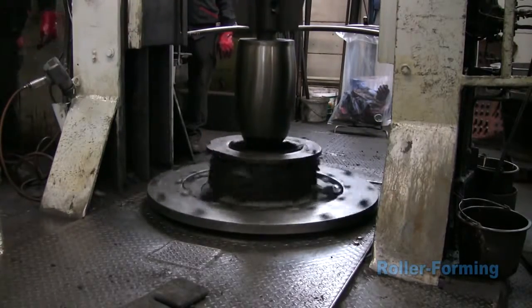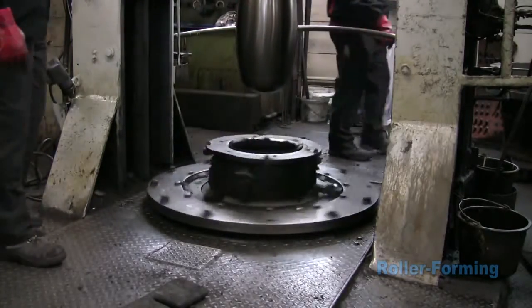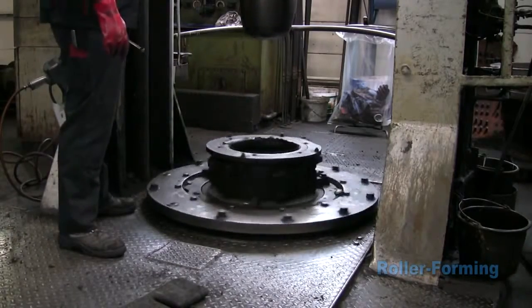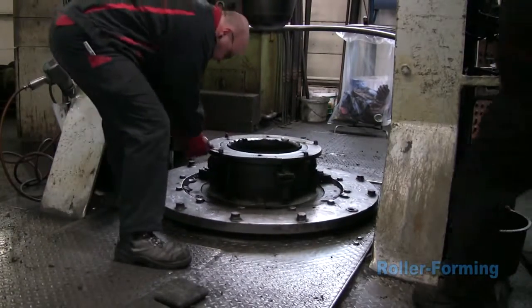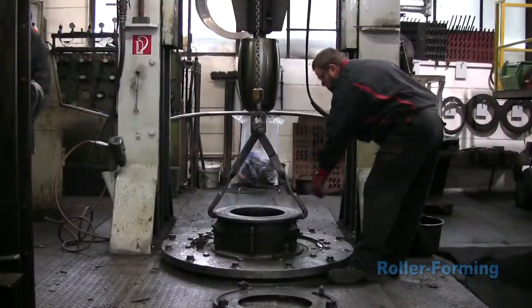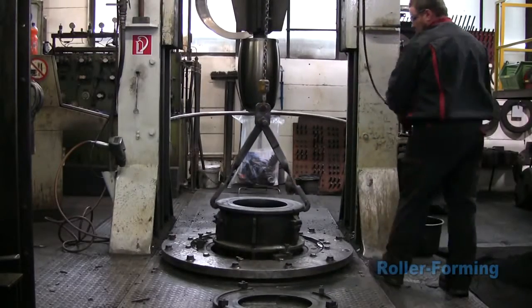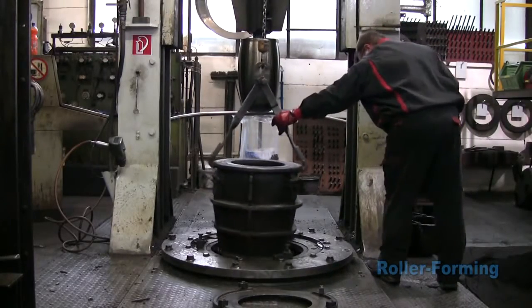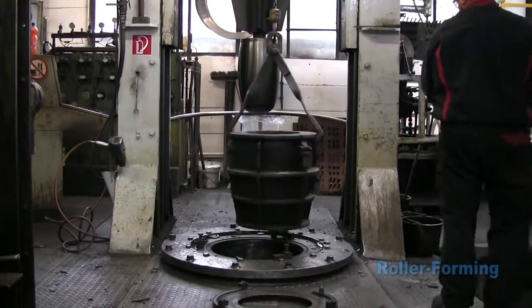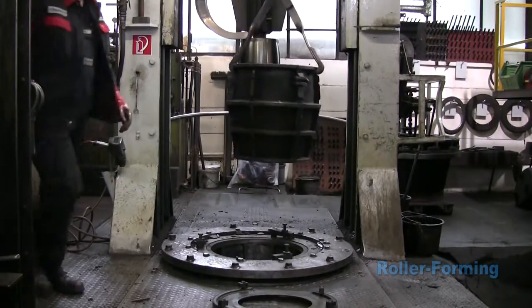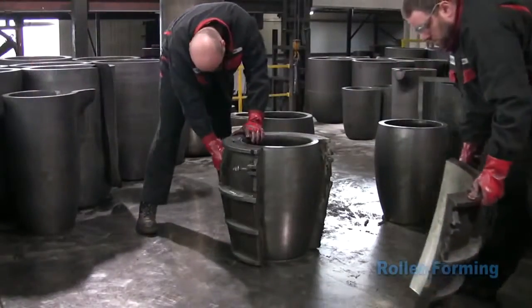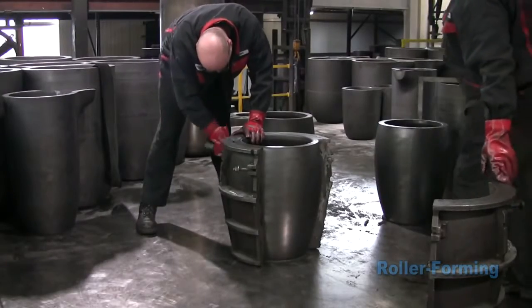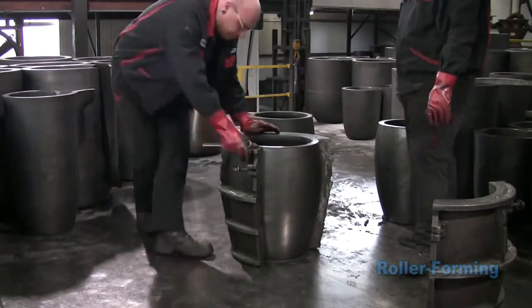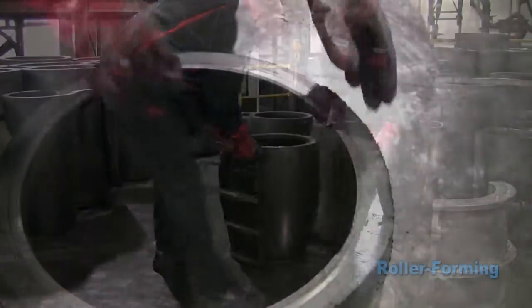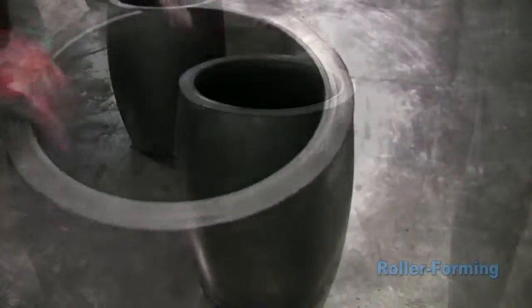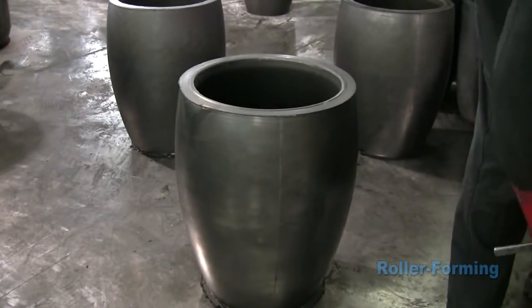Roller forming molds and rollers can be changed, allowing the system to be used for making a variety of crucible sizes and shapes. Our roller forming process produces a dense crucible with good thermal conductivity, excellent thermal shock resistance, high mechanical strength and refractoriness, and very high resistance to damage caused by fluxes. And because the roller forming cycle is fully programmed, every crucible produced has identical properties and offers uniform performance.